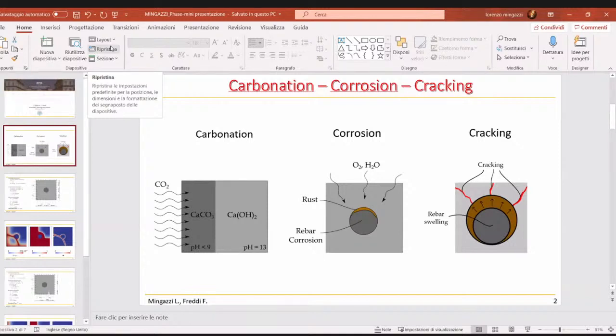Where we modeled the formation of cracks into the concrete cover via the phase field model for brittle fracture. In particular, we used a formulation which used the swelling of the rebar obtained from the corrosion process as a loading parameter, and we applied the damage field only to the positive part of the concrete strain energy, so we can actually accurately model the cracking phenomenon and the spalling as well.